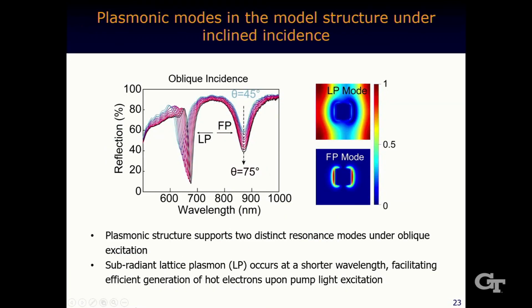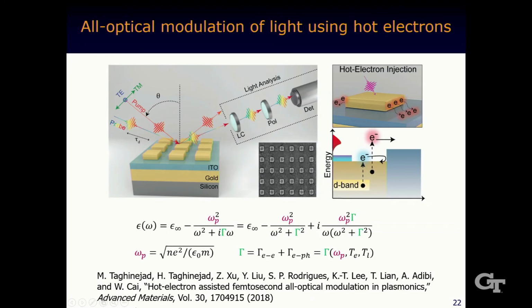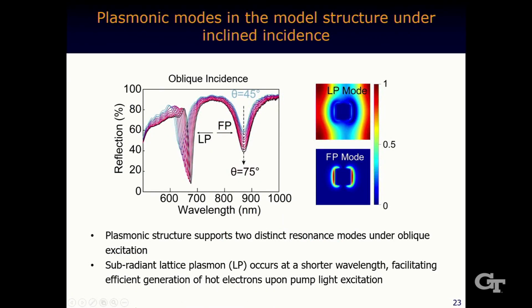So the device structure supports two resonance modes. One is at a longer wavelength, the Fabry-Perot mode, which is related to the geometry in most cases, and another mode related to the lattice, the so-called lattice plasmon mode. And this LP mode can be excited only by TM polarized light, and it features a very sharp resonance behavior. This is good because this means the plasmonic resonance here has a subradiant nature. It means that the radiative loss is very small so that all the incoming photons will be absorbed and almost all converted into hot electrons.